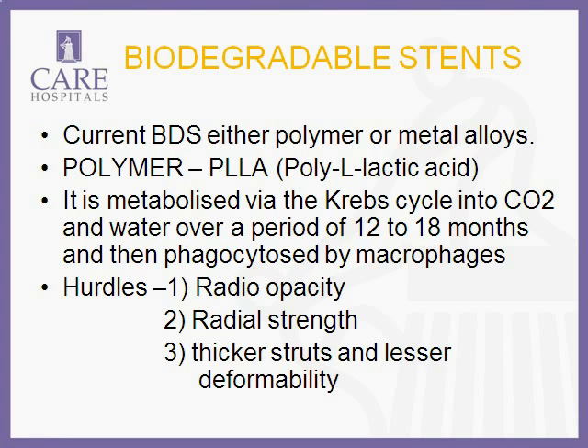Now, current biodegradable stents are either polymer-based or metal alloys. The polymer is generally poly-L-lactic acid, which is metabolized by the Krebs cycle and degraded into carbon dioxide and water, which is then phagocytized by the macrophages in 12 to 18 months. The only issue with this is that because there is no metal there, the radiopacity is very low. The radial strength is also very low.